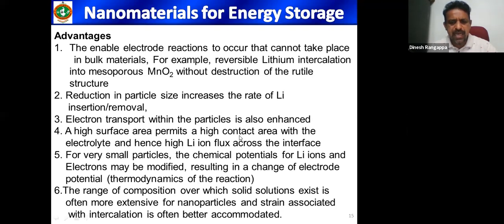A high surface area permits high contact area with the electrolyte, and hence high lithium ion flux across this interface. For very small particles, the chemical potential of lithium ions and electrons may be modified, resulting in change of the electrode potential. That means the electrode potential may be different for bulk particles and nanoparticles. The range of composition over which solid solution exists is often more extensive for nanoparticles, and strain associated with the intercalation is often better accommodated. So this has been proved with many solid solutions or doping obtained for electrode materials, lithium cobalt oxide and lithium manganese spinel structure. So we have also tried this kind of composition to improve the performance.